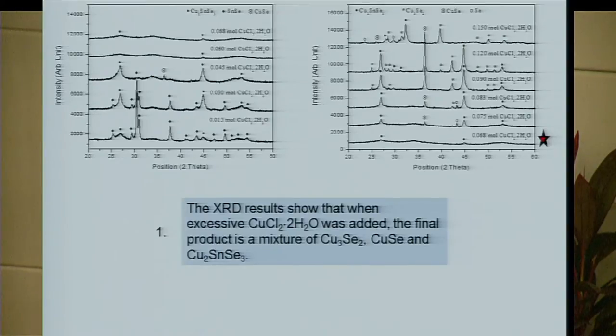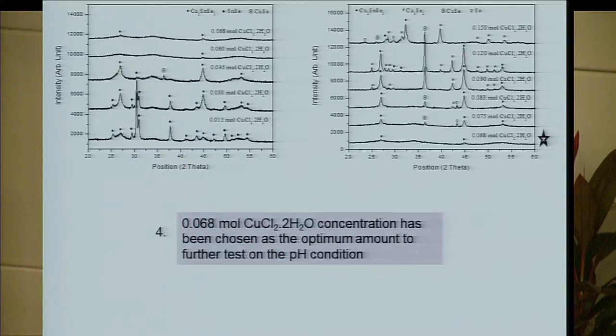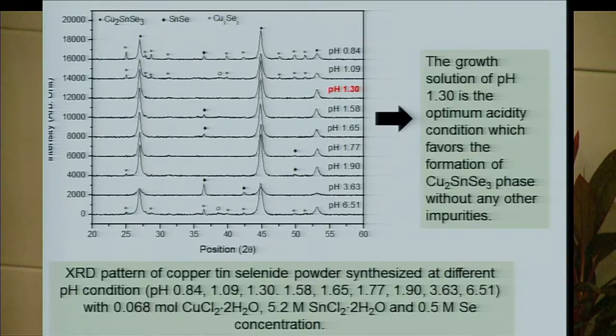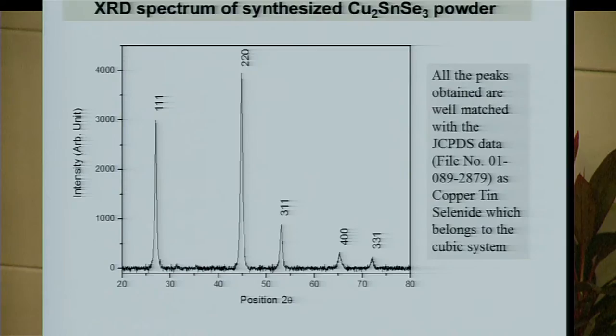And from there, we look at the optimized parameter, and then we use that optimized parameter and vary the pH. And this was what the chemists were advising us. So, and they were right. Yeah, they were right. And we got a very pure, clean copper tin selenide, as depicted in the X-ray spectrum.